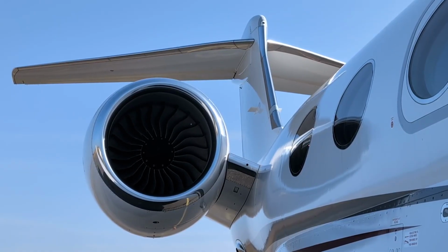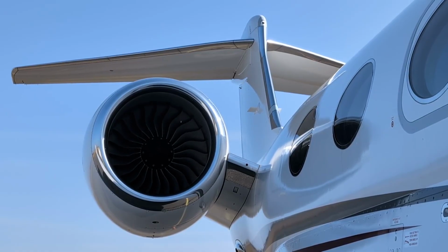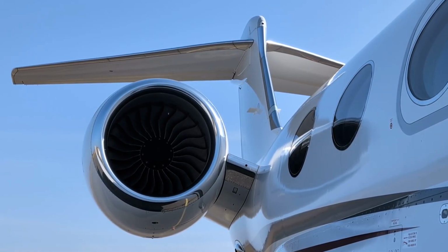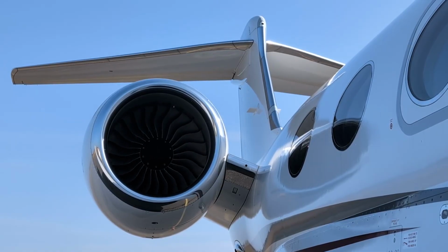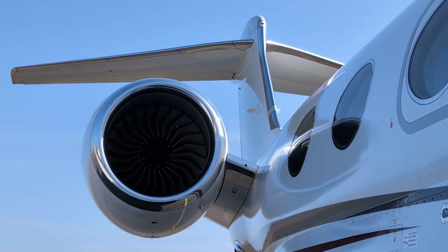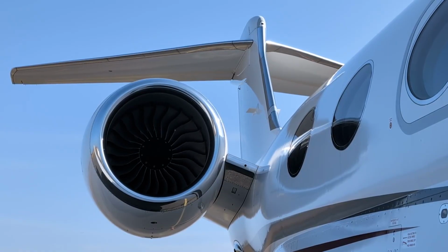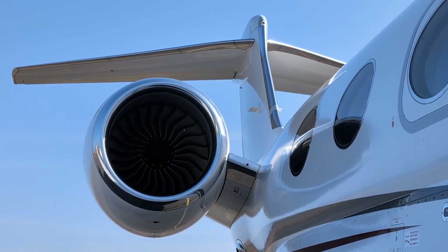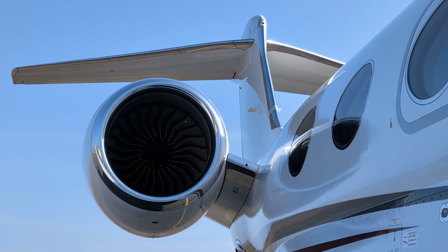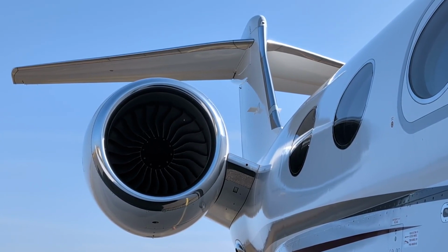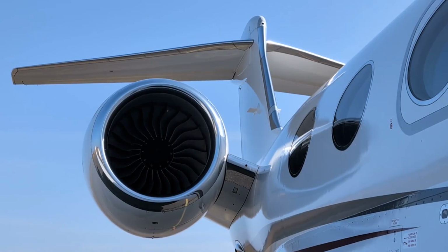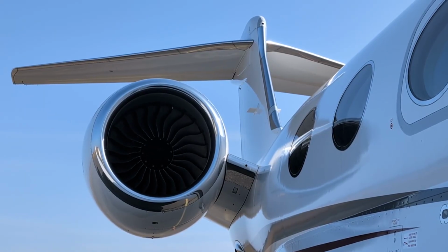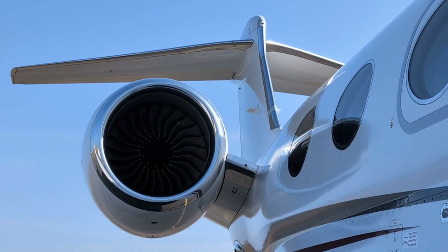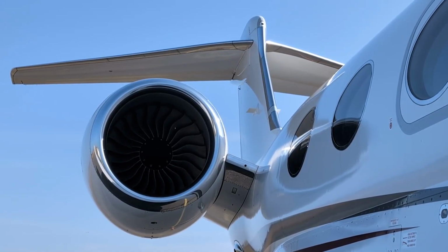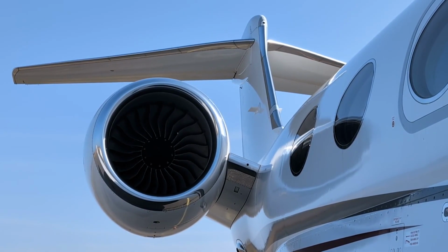So where did the crack come from? The NTSB traced it back to the manufacture of the disc itself. The titanium contained a metallurgical defect, an internal inclusion, essentially a hard, foreign region of material that never belonged in the finished forging. That inclusion became a stress concentrator. Cycle after cycle, every time the engine spun up and back down, a fatigue crack advanced from it. Fatigue cracking is patient. It moves a microscopic amount per cycle over years of service until the remaining material can no longer carry the load.